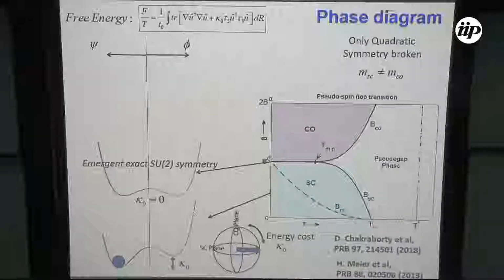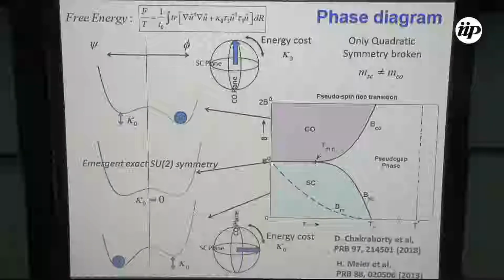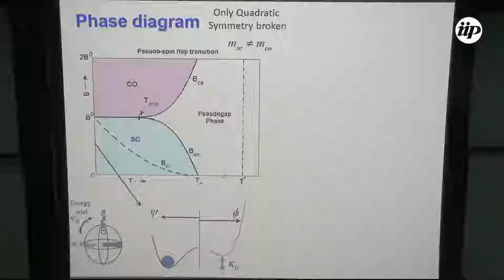If we increase the field further, as I said, the mass will go further higher, but then the charge order minimum will be lower. As a result, the system goes from superconductivity to charge order through a direct transition, and the pseudo-spin, which was lying in one plane, will now flop to the other plane, and there is a pseudo-spin flop transition. Before going there, I was talking just about the t equal to 0 line. So let's see what happens if we increase the temperature.